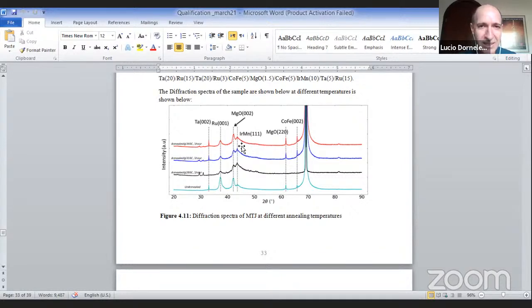You say that that's MgO 220, but I can assure you it's not, and there's a simple reason for that. You have the peak for the MgO 002 there. If this peak at 60 were MgO, it would be wider. There's no way for a peak from the same material to be thinner at higher angle, because of the width of the peak, that famous Scherrer equation. The crystallites that give the 002 peak are the same crystallites that give the 220, so they have the same size.